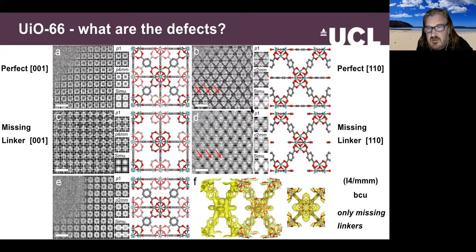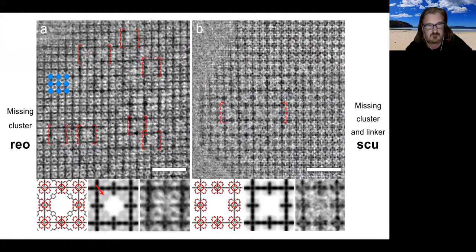Now, on investigation, it turns out that this sample also had areas like this. And here you can see that we have missing struts. So in terms of an atomic picture, we've lost those phenyl rings. And these happen in an ordered way in this particular part of the crystal. In fact, you can solve the crystal structure of this nanodomain within UiO-66, and it has a particular topology, which is called bcu, and a particular symmetry.